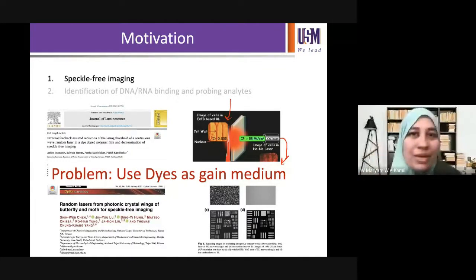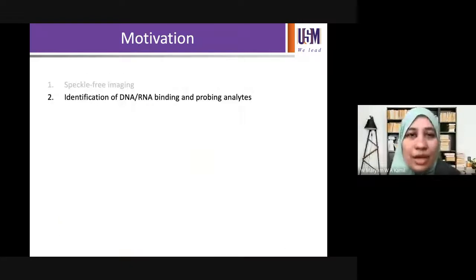Dyes, of course, can work to show the working principle, but in order for you to make it a working device, working with dye is not actually the best option. Number one, it is liquid-based, so you need to create some kind of capillary behavior as well. Number two, they bleach very easily. So the moment you have a high power, then it would degrade. The decay rate is very fast. Okay, so the degradation of the dye is an issue. So that is one motivation to replace the gain medium.